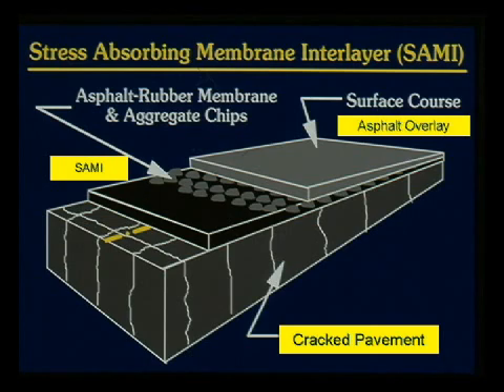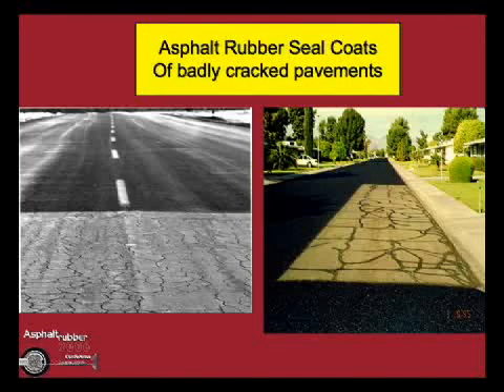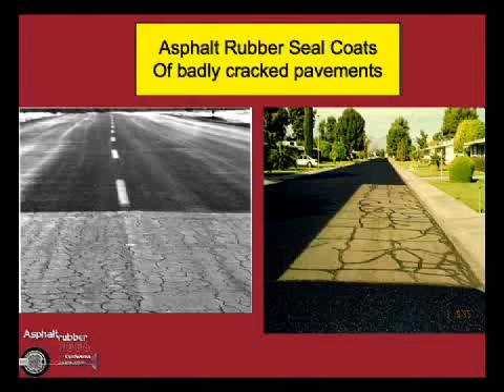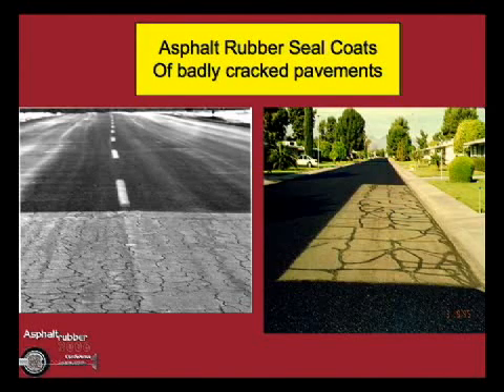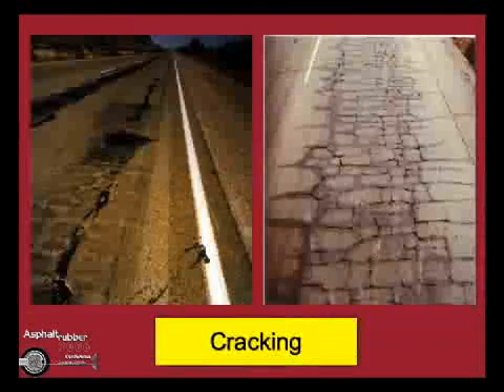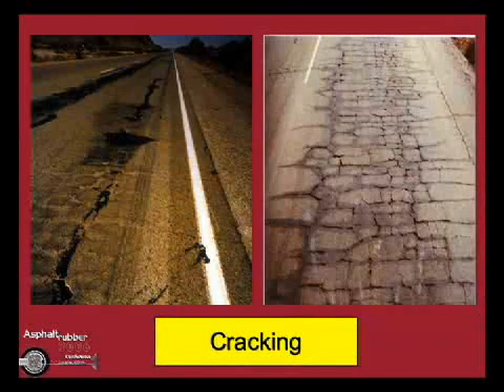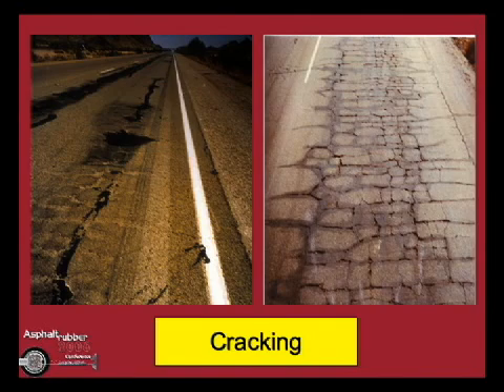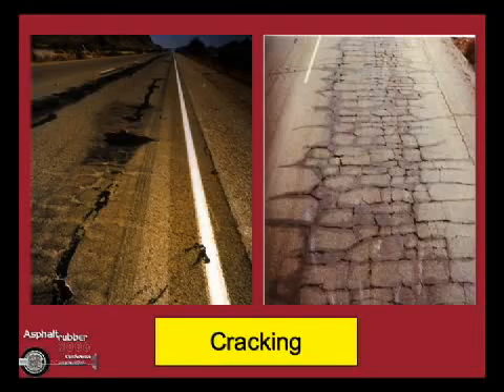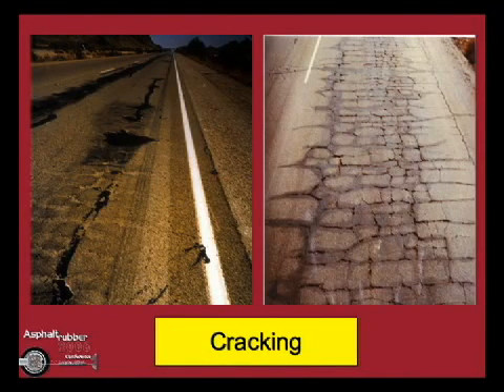Some of the early seal coat jobs were focused on really, really badly cracked highways. They were seal coating them as a temporary action, only to last a year or two until they got around to overlaying them. The way funding went in Arizona, sometimes that would take more like 5 or 6 or 8 or 10 years. So we learned a lot from these early seal coat jobs about the ability of asphalt rubber to retard reflective cracking. And cracking, indeed, is why this material was eventually adopted in Arizona: to prevent reflective cracks. In other words, when you overlaid a pavement of this bad a nature, you could prevent the cracks, or at least delay them for a very long time from coming through.